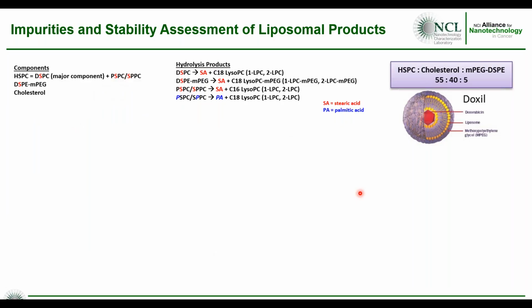Still looking at Doxil, we want to look at impurities and stability assessment. So Doxil contains HSPC, cholesterol, and lipid PEG. When these degrade with time, they basically give you the free fatty acid, so stearic acid. If you're looking at DSPC, we have palmitic acid at the PSPC. And we wanted to see if we can track the presence of these free fatty acids as a sign of stability of these liposomal products.